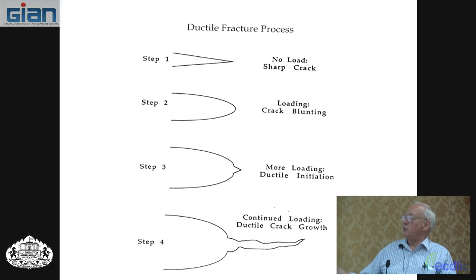You start with a sharp crack when you have no load. As you begin loading, that sharp crack can blunt. As you load some more, ahead of the blunted crack, you develop another sharp crack, which can grow in a stable manner. So this whole process can be stable, and what then is the difficulty is, where do you say fracture occurs? Of course it doesn't occur there, and maybe it's occurred already here, but you have to be able then to pick a point that you say this point is the fracture point.